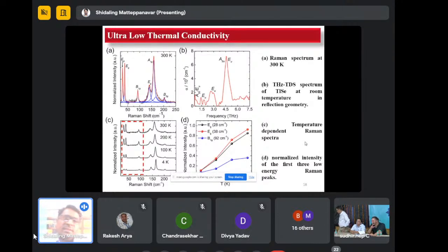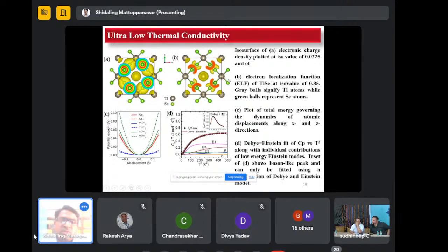So this thallium selenide material exhibits such a low thermal conductivity because of the presence of low optical phonon modes. From the Raman measurement, we can see that below around 50 centimeter inverse it is showing two main broad peaks, and they are basically the main reason for the low thermal conductivity, and it is confirmed from the terahertz spectroscopy measurement also. And these are the theoretical calculations. They well support our low thermal conductivity.